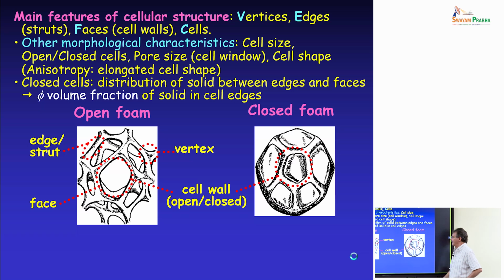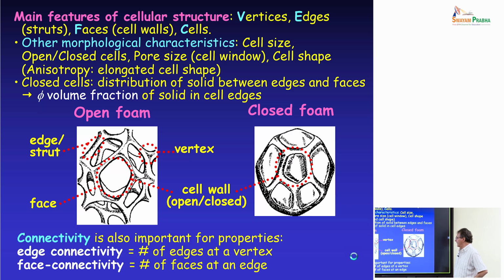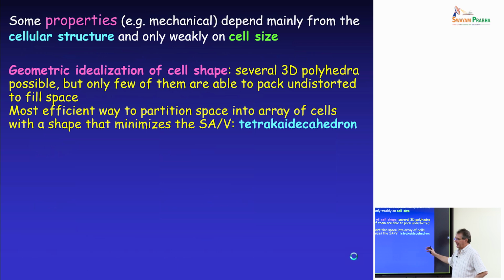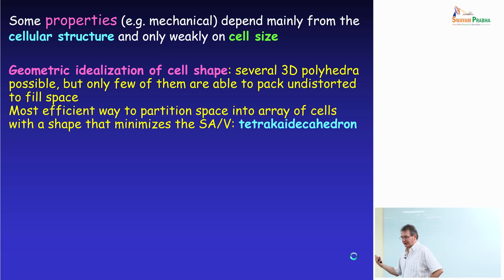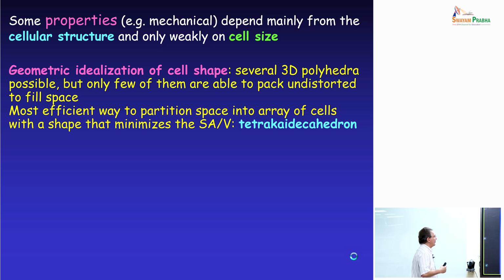And again, you can have open or closed cell walls. On the left, you can see it's open. On the right is closed. The connectivity, so the number of struts reaching each vertex, is important for the properties. And bear in mind that when you make a foam, you cannot typically control the number of struts going into a vertex. If you are, of course, using additive manufacturing, you can do that. There's an interesting point to make, that some properties depend mainly on the cellular structure and only weakly on the cell size.